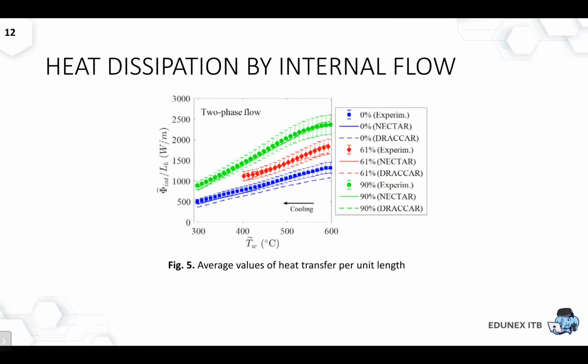And then this is the heat dissipation by the internal flow, the average values of heat transfer per unit length. As you can see in the picture, there is the DRACCAR term. We're just going to ignore the DRACCAR term because it's basically just another code. I only focus on Nectar and the experimental results. So as you can see, the lines are pretty much in harmony, the green one and the red and the blue one. So we can safely say that the experimental and Nectar results are pretty much the same.